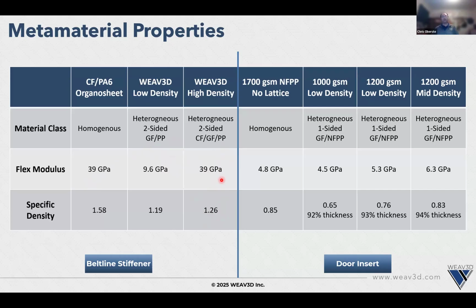On the door insert, that one is actually starting much lower. These natural fiber nonwovens are not structural, so they only have a modulus of about 4.8. The 1000 GSM with a low density lattice pattern is about 4.5. But it's also a fair bit thinner. So it's about 92% of the original 1700 GSM's thickness. That's partly just because of how they compression mold it. They don't compress it 100% to its minimum size, so it's not quite the ratio of the weight reduction, but the density still goes down.